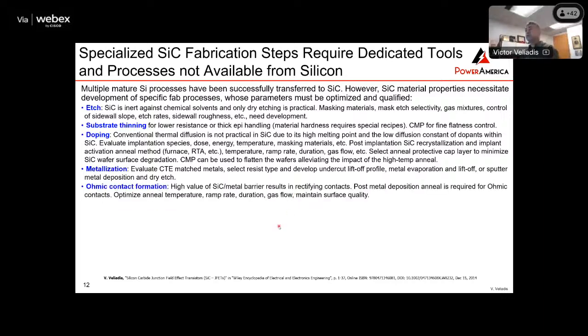Another one is the ohmic contact formation. In silicon, if you put a metal layer, you're going to get an ohmic contact. In the case of silicon carbide, because of the large band gap, if you put metal on silicon carbide, you're getting a Schottky. So if you want a low resistivity ohmic contact, then you have to do certain processings. You have to go to high temperature and do a silicide, and I'll talk about some of these things.